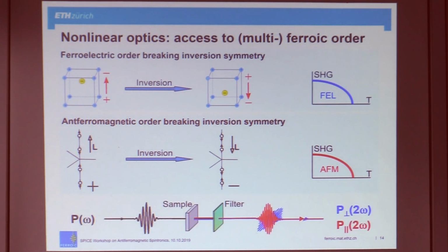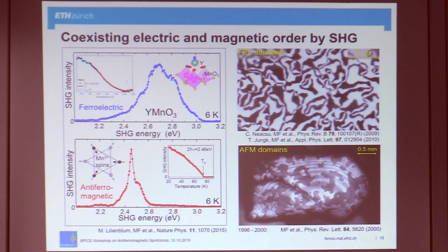So that's then a typical experiment. Light at frequency omega coming in. A sample doubles it. Then you separate with a filter. You block the omega component. And then you analyze your two omega component with respect to contributions that couple to one or the other order. Here you see an example. Yttrium manganite is just any compound that has ferroelectric order and that has antiferromagnetic order. So at the ferroelectric ordering temperature, first of all, you see a certain spectral dependence of this signal, and the signal goes away right at the Curie temperature, the ferroelectric Curie temperature.